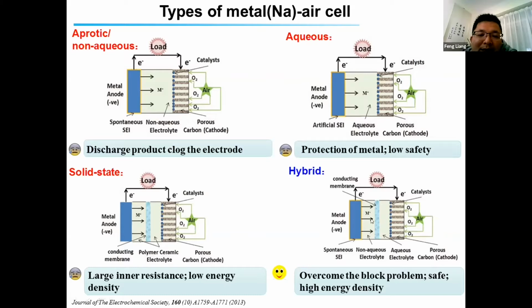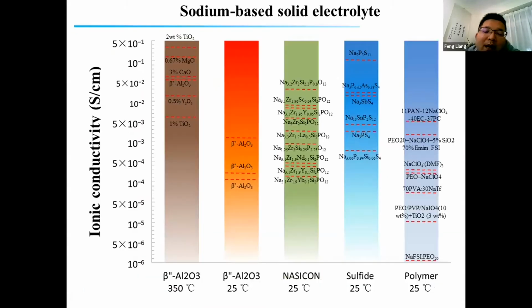Also, we didn't use the polymer electrolyte, so it has a relatively high ionic conductivity, and it leads to a battery with a high energy density. So our research is focusing on this hybrid sodium battery. In order to prepare this sodium battery, the most important thing is we should select the solid-state electrolyte with a high ionic conductivity and good stability.